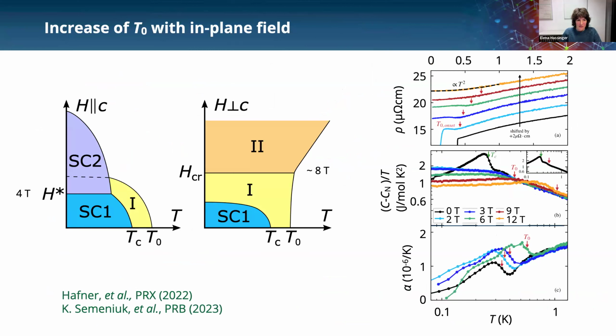Okay, and the behavior of this phase in magnetic field is very anisotropic, so we call it phase 1. When we apply a field along the z-axis, it's suppressed at a field larger than this transition between the two superconducting states, which is roughly at 4 Tesla. So we follow this line, and it seems to meet here at roughly 6 Tesla. And maybe I should briefly mention that there's still a bit of a debate whether this line is meeting the H-star line. But in our measurement, it looks like this.